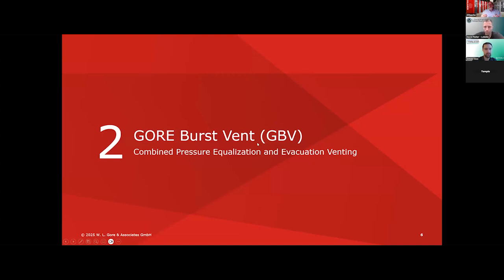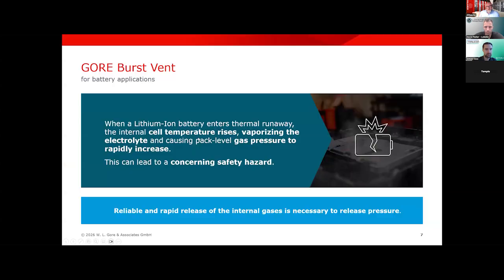It's a combined pressure equalization vent with evacuation venting capabilities. And you all know the lithium-ion batteries. If they once enter a thermal runaway, the internal cell temperature rises, vaporizing the electrolyte and causing pack level gas pressure to rapidly increase. And this is concerning the highest safety hazards, what we've seen in the picture before.